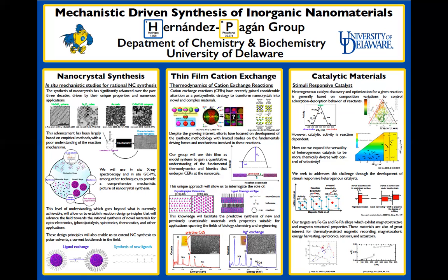And if you take a look at the figure on the left of the copper sulfide, post-synthetically, the cations were swapped while the yellow anions remained unchanged. This allows for the formation of non-equilibrium crystallographic phases, which in turn presents access to structures that would be challenging to synthesize directly. Additionally, cation exchange reactions allow us to access diverse morphology portfolios, retain the size and shape of the nanocrystal, and can be reversible.